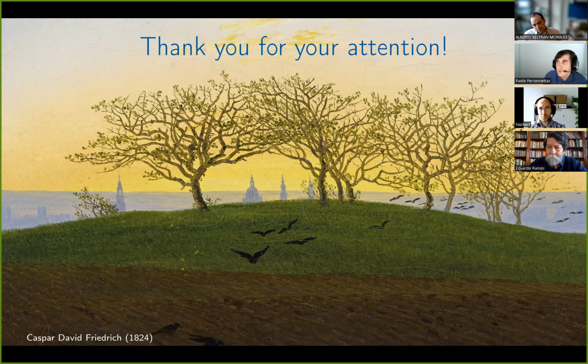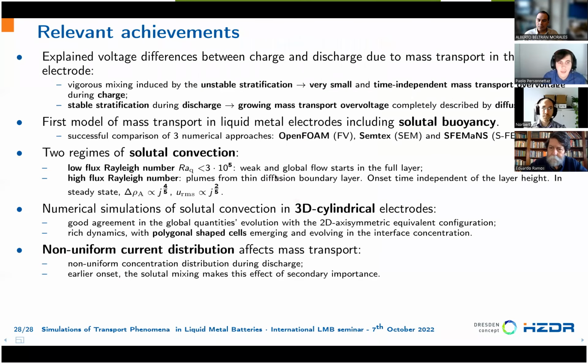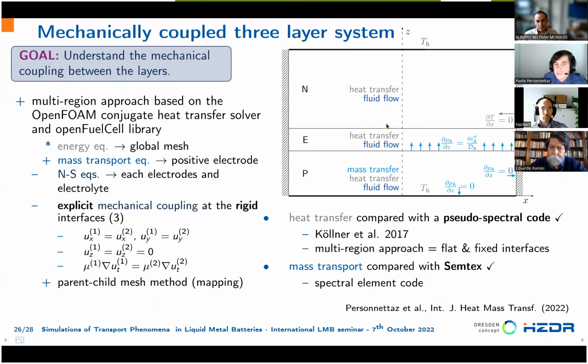Yes, we study both together in a paper that I didn't present because the presentation was really focused only on mass to not make everything too heavy to follow. We have a paper in which we use the multi-region solver that I discussed before, and we solve heat transfer in the 3 layers and heat and mass transfer in the positive electrode. And what we observe is that, for example, during discharge, we have some internally heated convection in the electrolyte, but this is not able to affect the concentration distribution in the positive electrode. Not even when you consider this mechanical interaction? Yeah, not even when you consider this mechanical interaction.